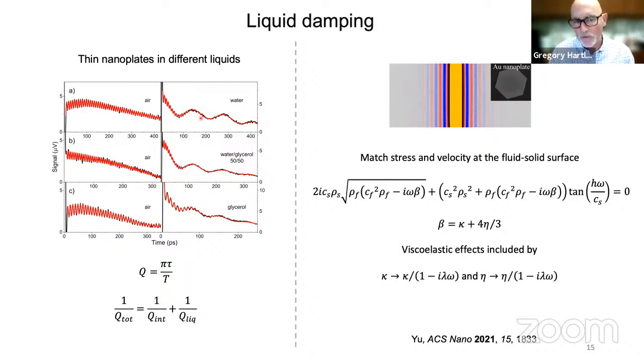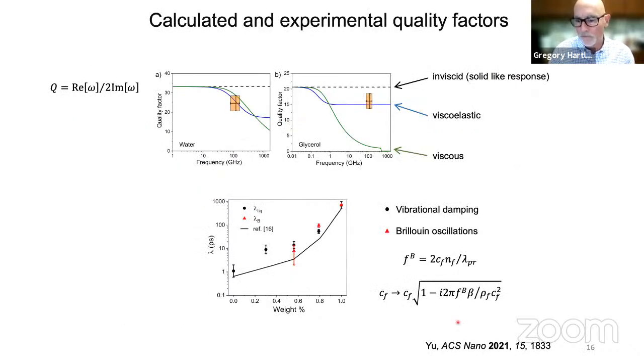So it turns out, because these Brillouin oscillations involve the speed of sound in the liquid, they also are sensitive to viscoelastic effects. And so you can also estimate the time scale from the Brillouin oscillations. And so everything's actually in pretty good agreement. So we can see, because of these high frequencies that we make with these nanomaterials, we see viscoelastic effects, and we can use that to measure a relaxation time for the liquid.